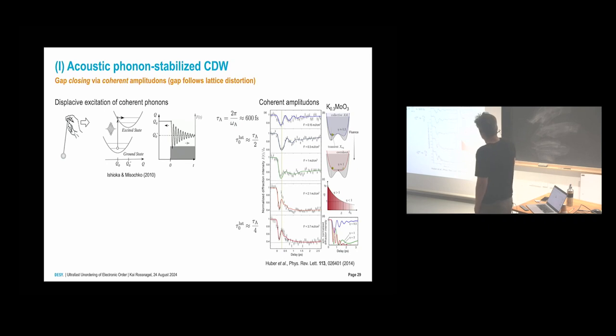Okay, and let's start with a simple scenario 1. So this conventional Peierls instability. How do you undo your charge density wave? You have to remove the periodic lattice distortion, and this you do by displacive excitation of coherent phonons. You excite your system and you move this potential, and then all your atoms start to oscillate in this cosine type vibration. And so if you go to 0 displacement, and this is very well known, and people see this in diffraction. So you see these oscillations in the Bragg intensity of your superlattice peaks, and this is the frequency of the amplitude mode, and in this material here it's 600 femtoseconds.